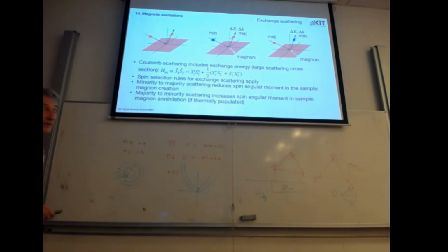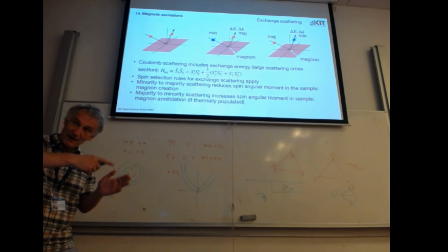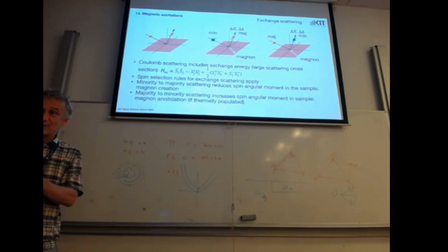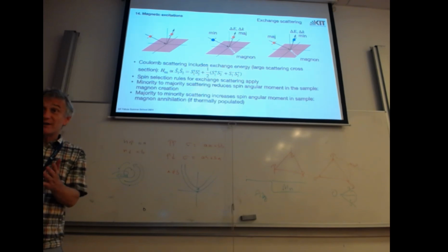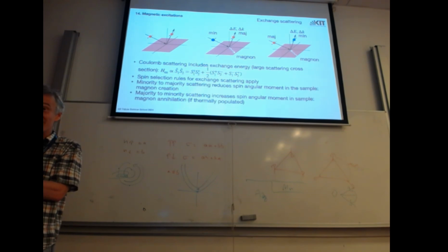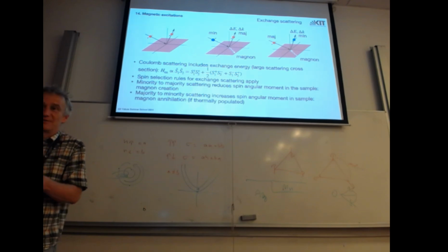You have the same momentum conservation. So this is a free experiment. You go from a sample, let's say, above the work function to an electron above the work function. Now with STM, I come in with the electron below the work function, and I end up with the electron below the work function. Yeah, but then because it's a tip, I no longer have this conservation. This scattering happens at the electron. So my electron comes into the sample. It's a Bloch state then. And this Bloch state scatters into another Bloch state via energy and momentum and spin exchange.